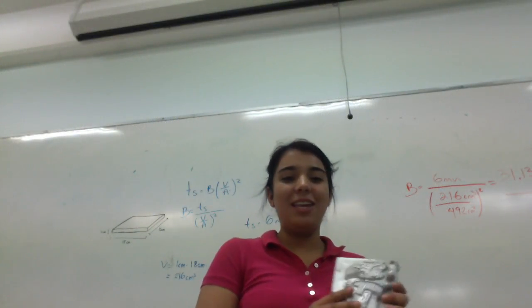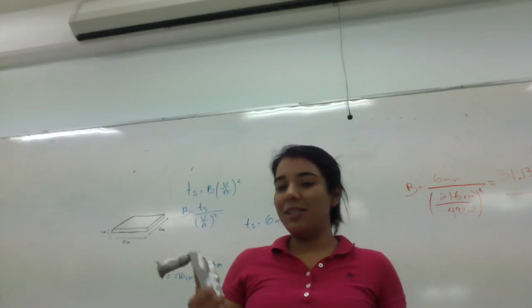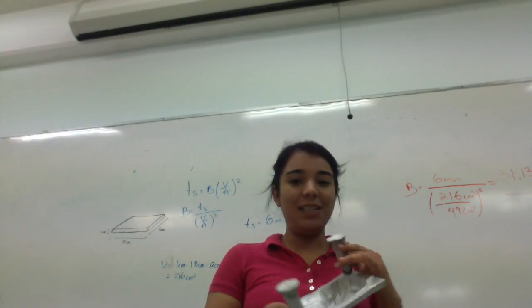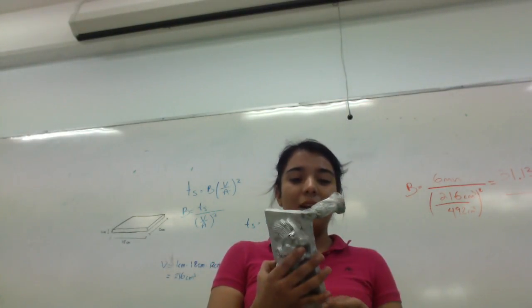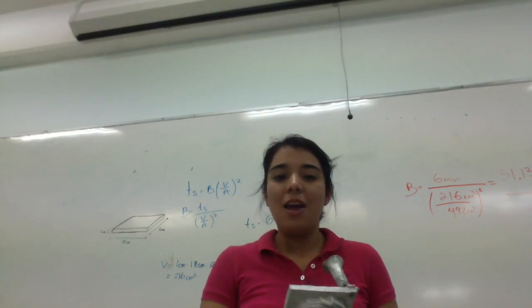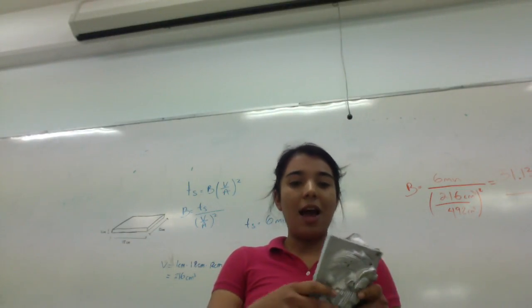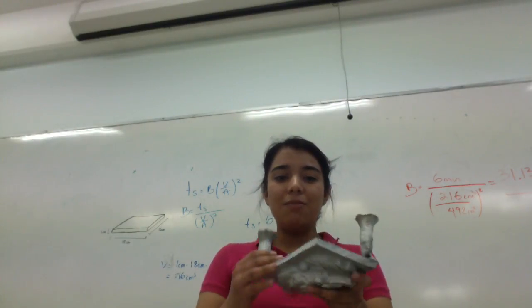The contraction cavity can be avoided by using a riser. For example, in our piece, the screw holes were for pouring the liquid aluminum, but they worked as risers too, making pipes more difficult. When the solidification process was finished, we could see some defects in our piece, like ruggedness that could be produced by a small mistake when compacting the sand, or by the pouring rate, which must be constant in order to obtain a uniform surface.